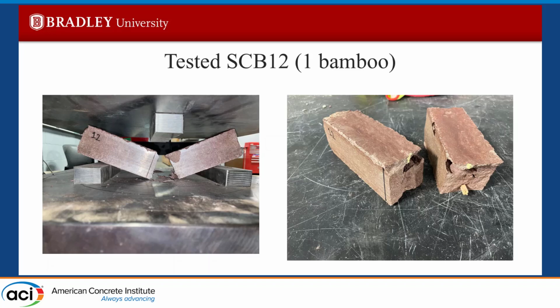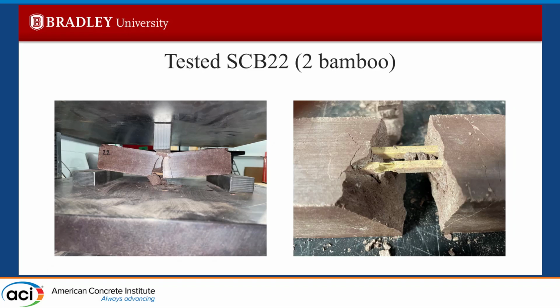But as you go to 2 bamboo, as you can tell, the specimen itself did crack, but it did not go fully through the bamboo, which is a good finding, and which just shows as you add more bamboo, the ductility will increase in the specimens.